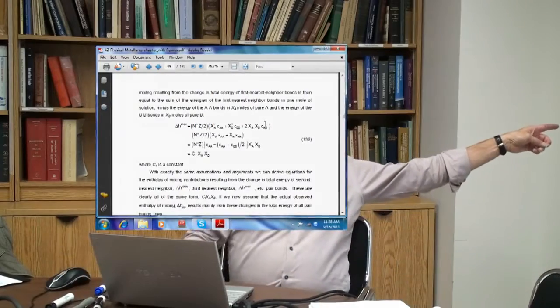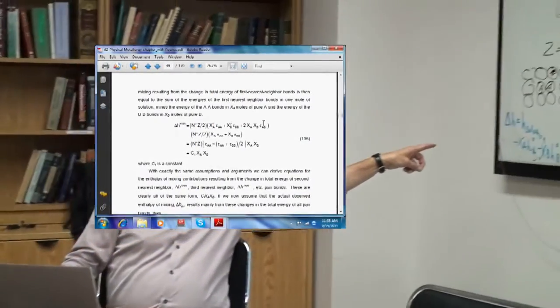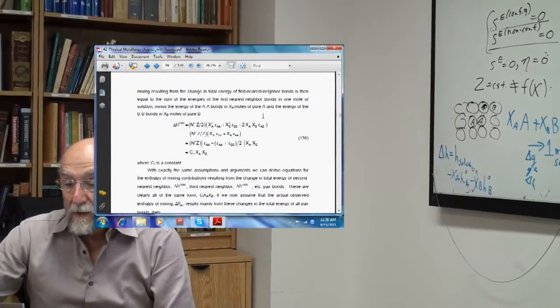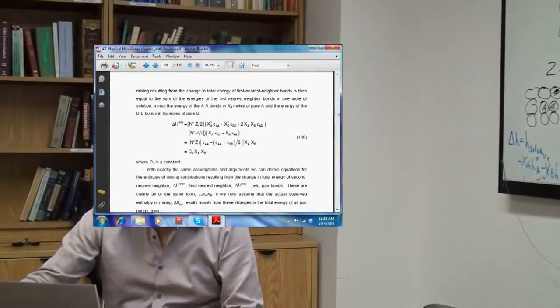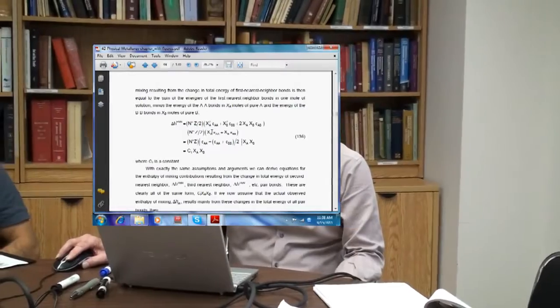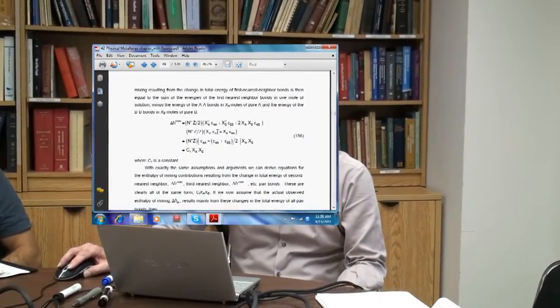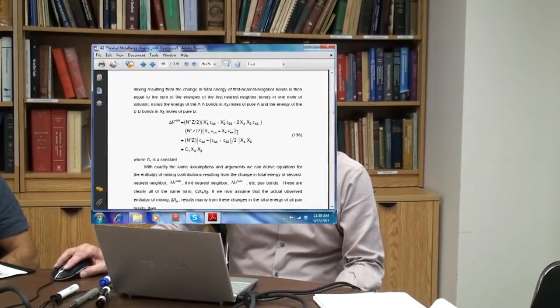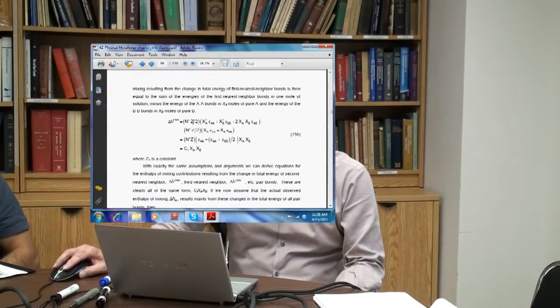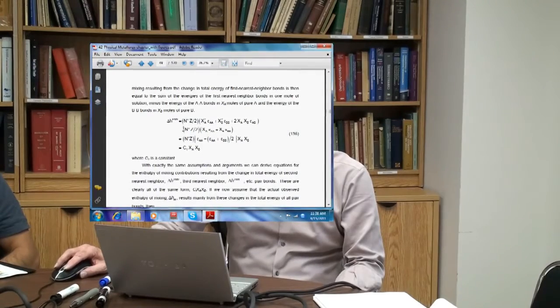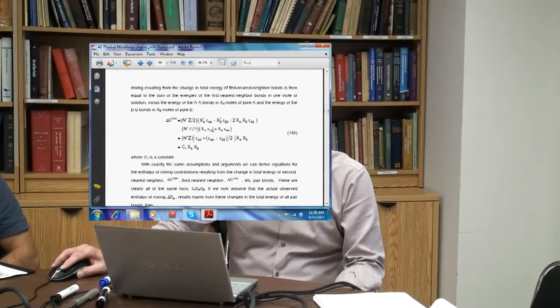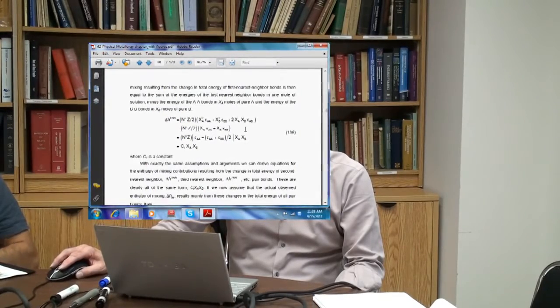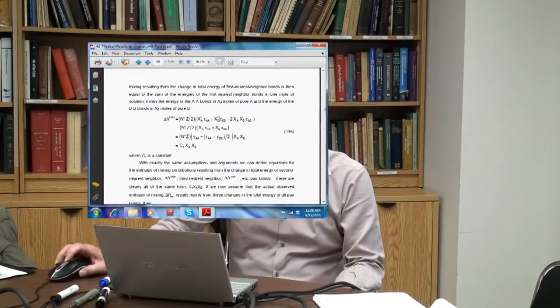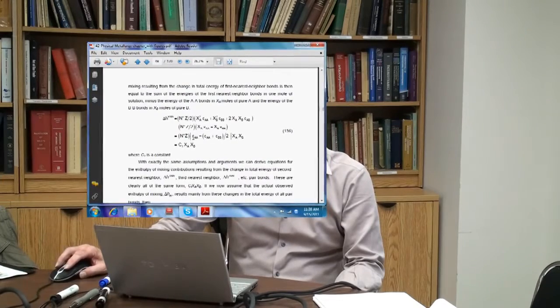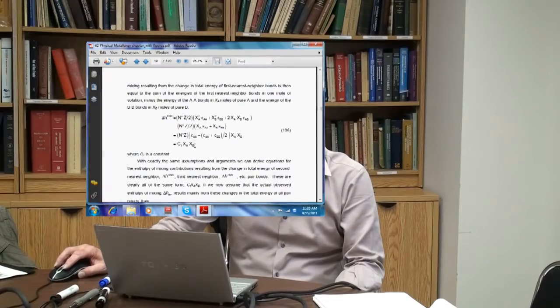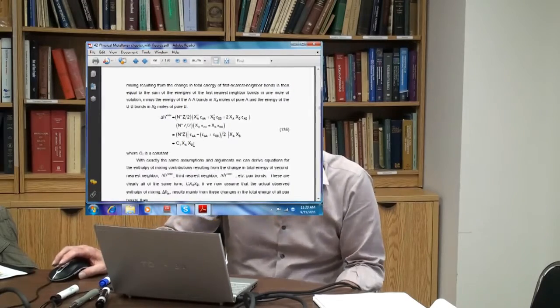From that now we have to subtract the energy of the bonds in XA moles of pure A. So that's the number of bonds in a mole of solution. That's the number of moles of A, XA, and all the bonds are AA bonds, plus XB times epsilon BB. So, energy of the first nearest neighbor bonds in solution minus the energy of the first nearest neighbor bonds in the pure A reactant and in the pure B reactant. If we put these together and collect terms, we end up with this equation, remembering that XA plus XB equals 1.